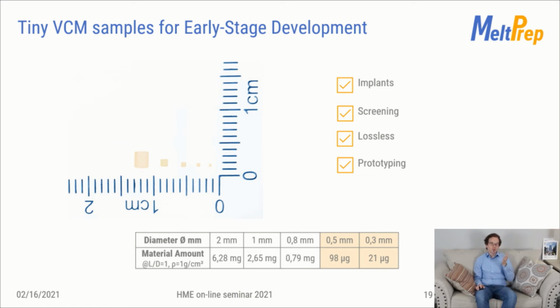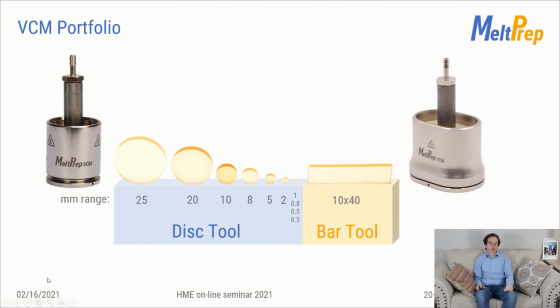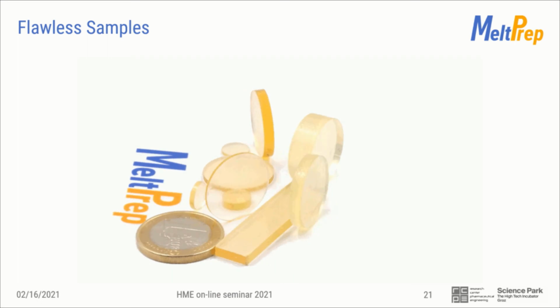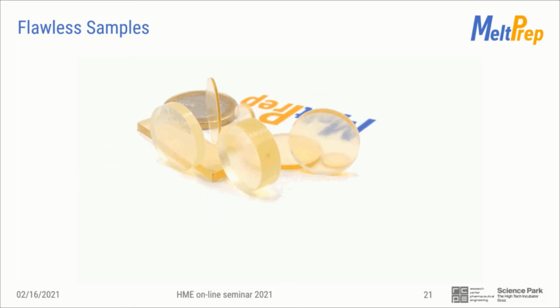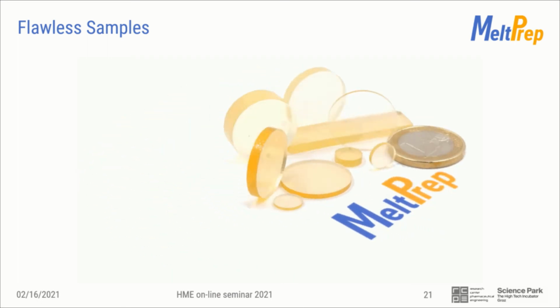The entire portfolio of dimensions you can produce with our VCM tools is shown on this slide. You can make disc-shaped samples with a diameter between 25 mm and 0.3 mm. We also offer a VCM bar tool that allows the production of a rectangular bar with 10 by 40 mm. This is used a lot for characterization of mechanical properties. Do you like these flawless samples here on this rotating video? Each of them was produced in less than 10 minutes.